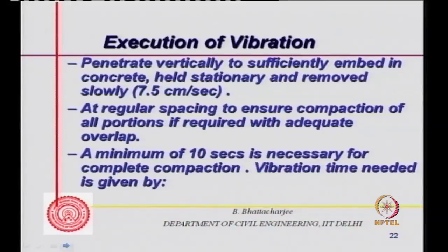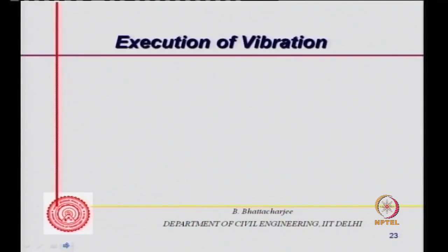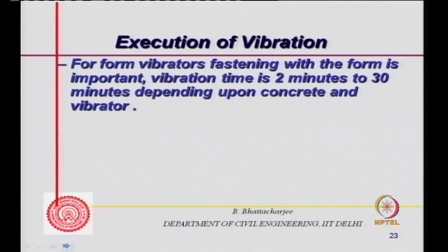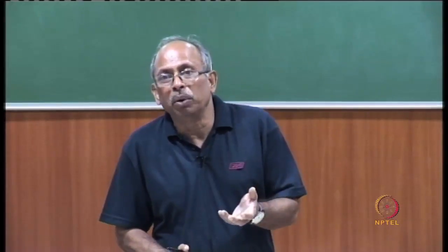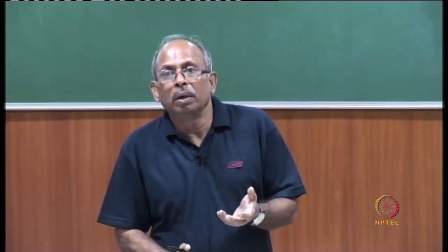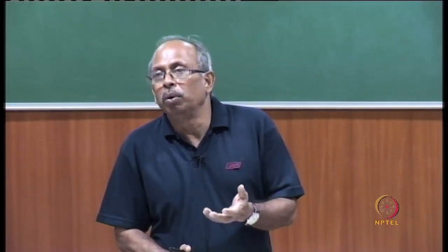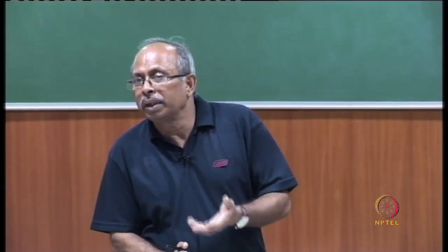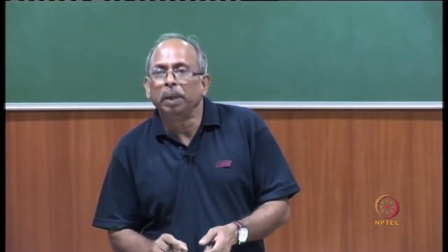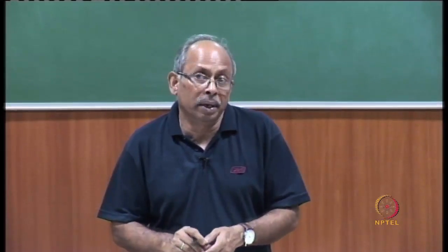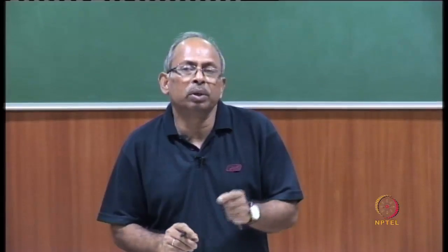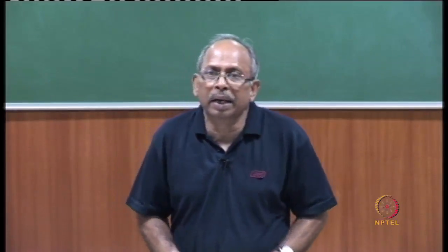Minimum usually 10 seconds is necessary for complete compaction. Vibration time needed is given by some equation, but I am not talking about that because nobody is going to use equations much. But we understand that at least 10 seconds if you keep it, and when you see the motor has come out, you pick up the needle vibrator, lift it up slowly at a very slow velocity, and you can see the slurry right at the top.